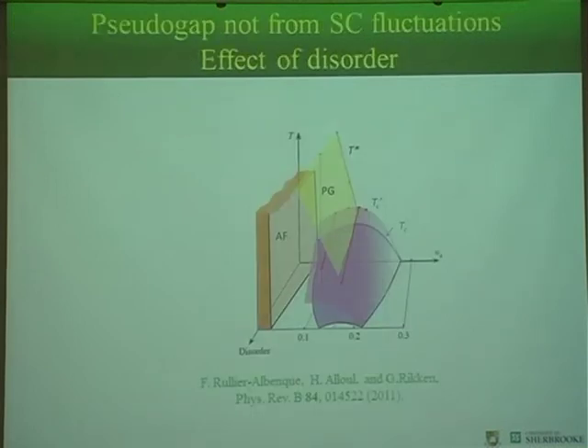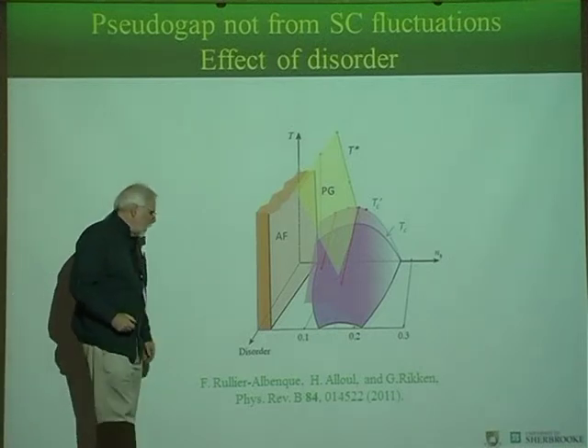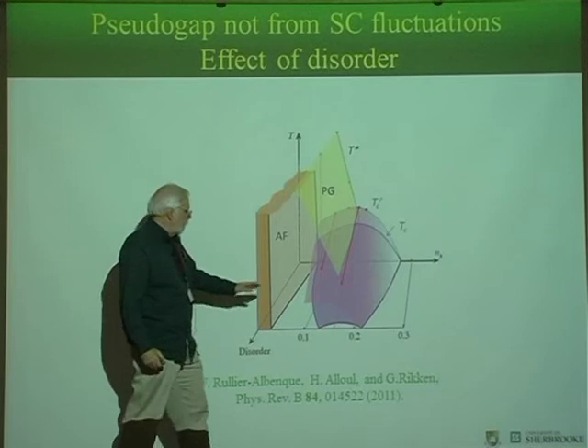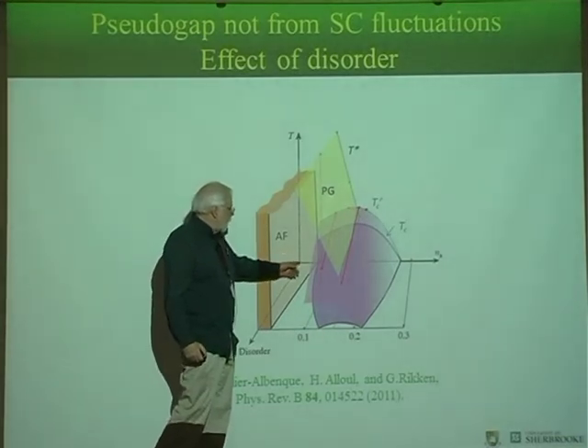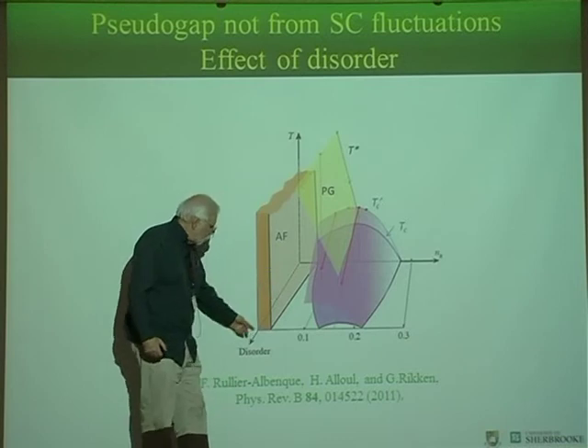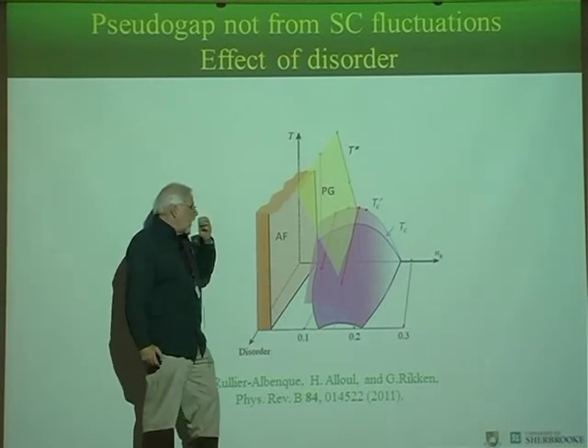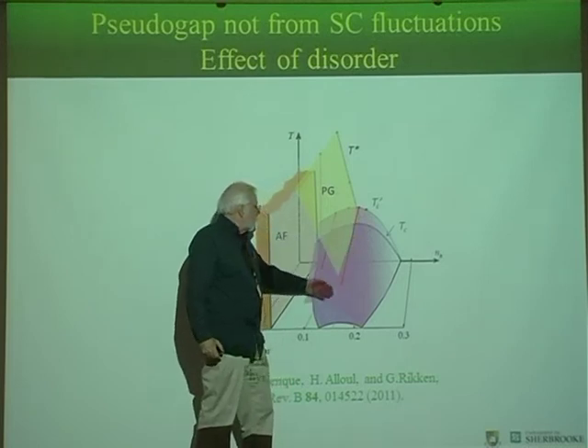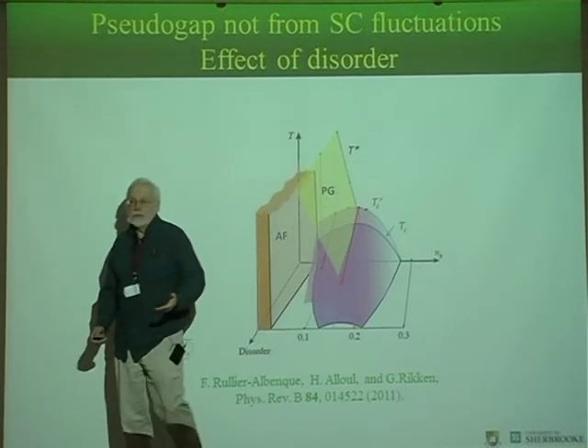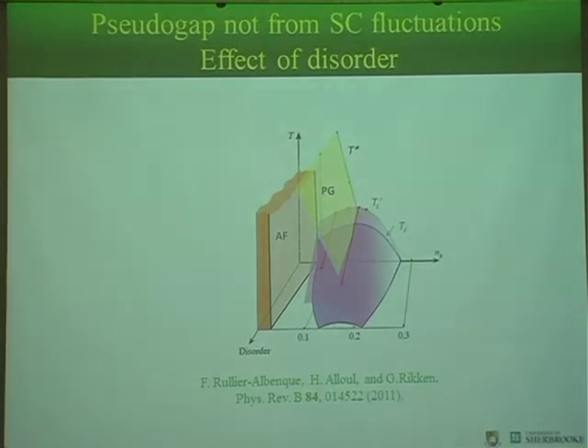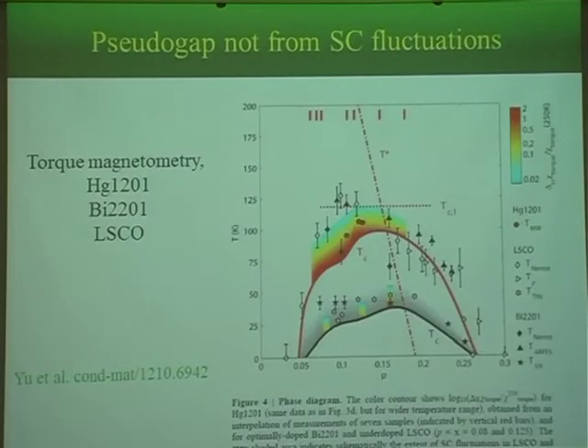Okay, the last statement that I'm going to make, which is a little bit disconnected, is to say that the pseudogap does not come from superconducting fluctuations either. For example, there are these experiments of Alloul, Rullier-Albenque, and Rikken that looked at the phase diagram as a function of disorder. Now they added another variable. And clearly, Tc depends a lot on disorder, but the pseudogap itself is very much independent of disorder. So that's one indication that pseudogap and superconducting fluctuations are different.